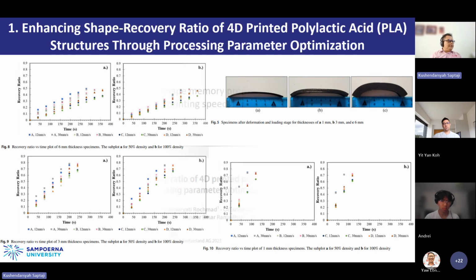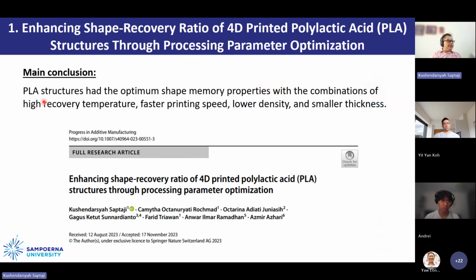From here, we find that the PLA structure we created had the optimum shape memory properties with the combination of a high recovery temperature, TR, a faster printing speed, lower density, and also smaller thickness. At smaller thickness, the recovery is better compared with the thicker sample. This work has also been published in Progress in Additive Manufacturing, only 2 years back.